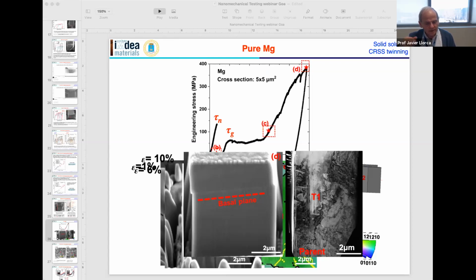So we conclude that the critical resolved shear stress for twin nucleation is higher than for twin growth, that aluminum in solid solution increases the critical resolved shear stress for both twin nucleation and growth, and the Labusch model is okay for dilute conditions, but it's not okay when you have higher concentrations. So at the end of the day, this is just a summary. With this technique, we have been able to measure the critical resolved shear stress for basal slip, for twin nucleation, for twin growth, and also for pyramidal slip.